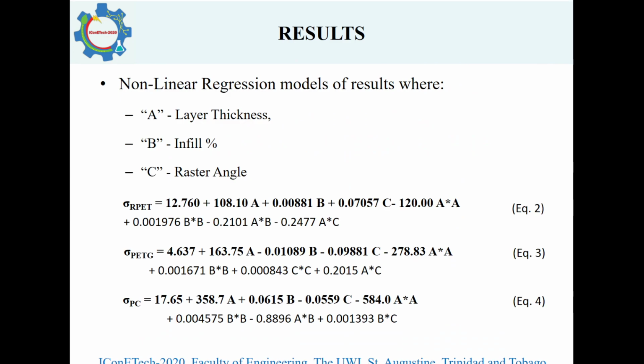For A being the layer thickness, B being infill percentage, and C being the raster angle, nonlinear regression models were created for each material to model the experimental data collected to determine the relationships between the print parameters and the flexural strength. Residual plots and main effect plots among the 3 materials were similar in that the model followed the assumptions of normality and non-discernible patterns. Further, by the interaction and surface plots for the 3 materials, it was apparent that infill percentage had the highest impact on the flexural strength, where the higher the percentage, the stronger the sample. Finally, the raster angle had the least significant impact on the 3 materials.